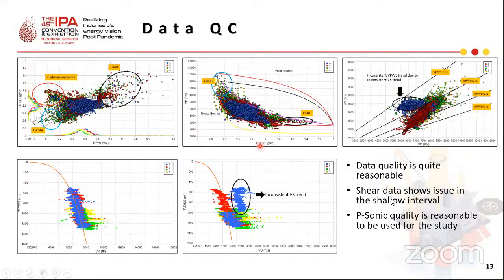The second crossplot is density versus VP, where again, we could identify the different lithologies. Also, we could check the consistency between the wells. Most of the data points here are generally in good condition. The third crossplot is between VP and VS overlain by constant VP by VS lines. In here, we can see that well A in blue color shows an inconsistent trend.